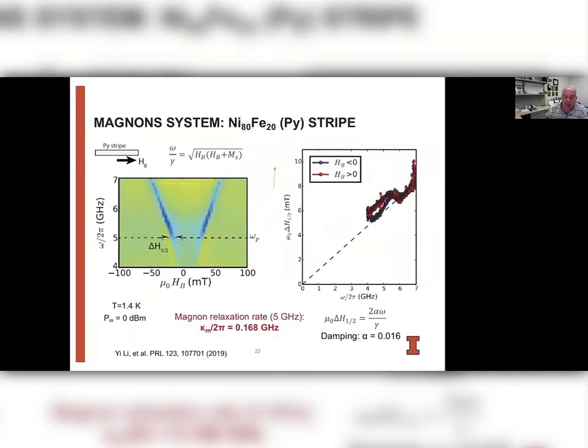So now we look at the system together with the permalloy stripe, and the first thing that we want to do is just characterize the dynamic properties of the permalloy by itself. So for this, what we do is we measure at 1.4 Kelvin, but at relatively high input power, 0 dBm, which renders the superconductor actually normal. And so we can measure the resonance of the permalloy as a function of magnetic field. And we see that the behavior is typical Kittel-like, nothing surprising there.